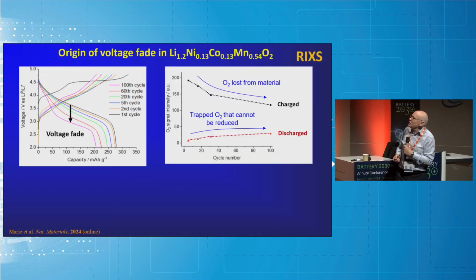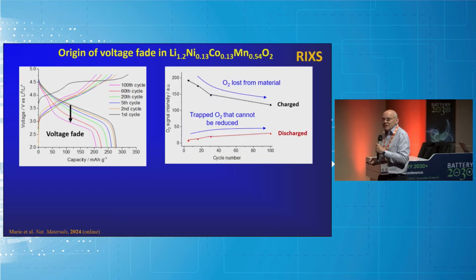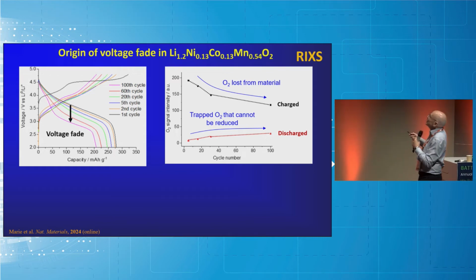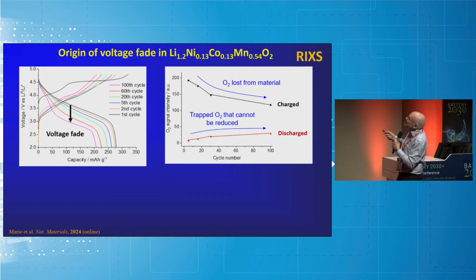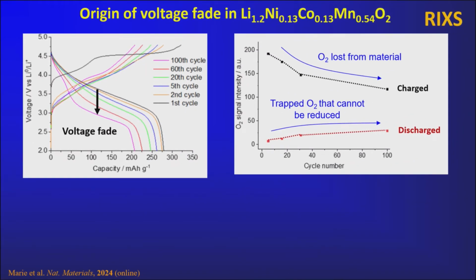So what we did is we used RIXS to look at what happened to these materials as you cycle. This is 100 cycles, and we've measured the intensity of the RIXS at the top of charge and at the bottom of discharge. Basically what you see is a drop in the oxygen O2 signal with cycle number at the top of charge. So that's telling us that we're losing oxygen from the material. And as I said before, it was initially thought that everything that happened on the first cycle was O2 loss. It isn't, but you do always lose a little bit of O2 every cycle.